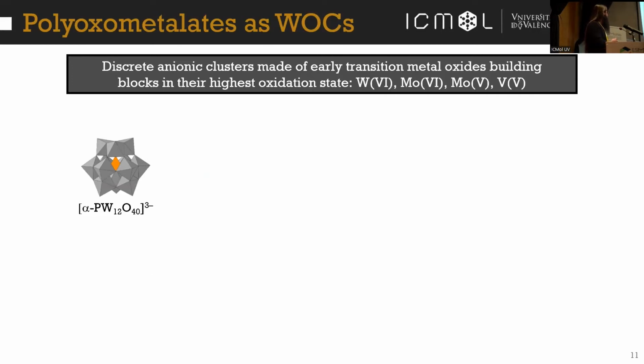It's a discrete anionic cluster made of early transition metal oxide building blocks in their highest oxidation state. And I'm presenting here what is called the Keggin moiety, or the Keggin archetype. In this Keggin archetype, we have 12 metal atoms. In this case, they are tungsten, which are placed in the center of these octahedra. In the vertices of the octahedra are placed the oxygens. And then we have a heteroatom, which in this case is phosphorus, and is shown here as a tetrahedron in orange.